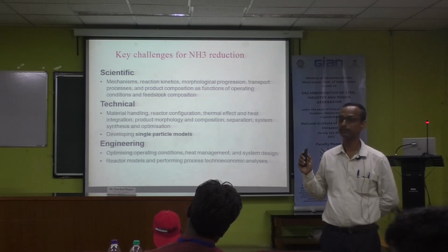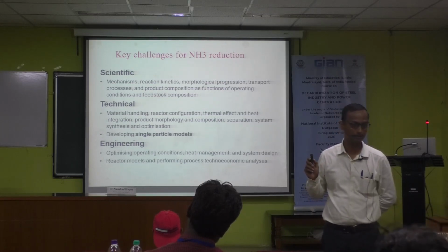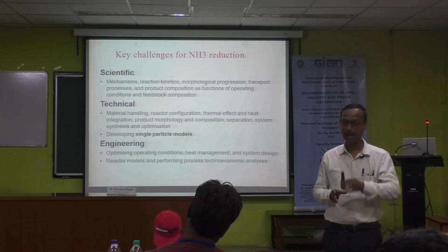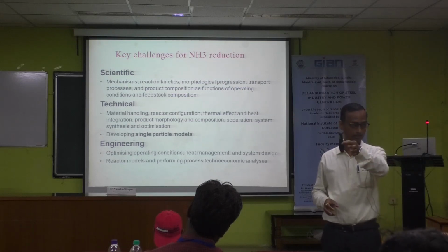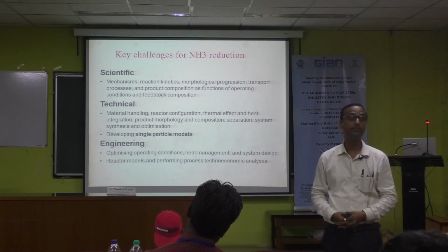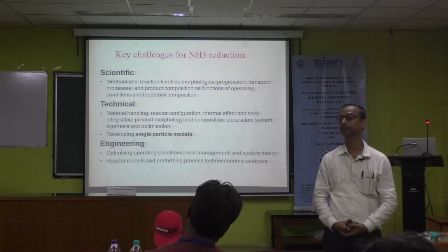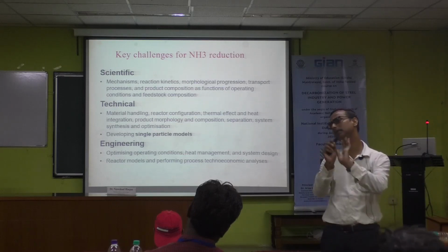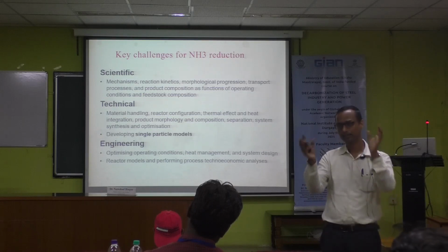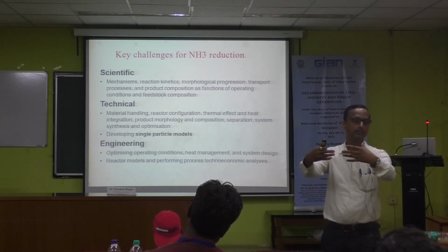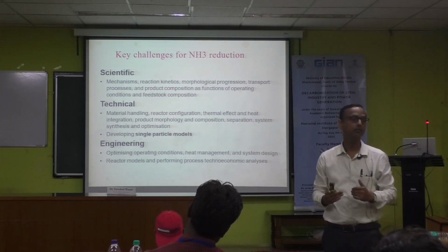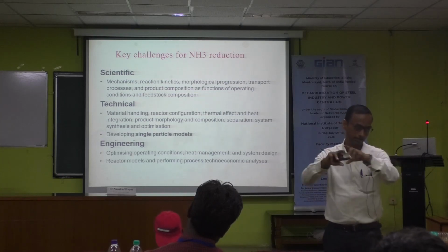These are some designs from IIT Hyderabad. Heating from both sides means at the core there will be less heating, and at the surface there will be more heating, if the heating system is from outside. Suppose your heating system is from inside, the opposite problem will be there: near the center core there will be more heating, and on the outer side less heating.